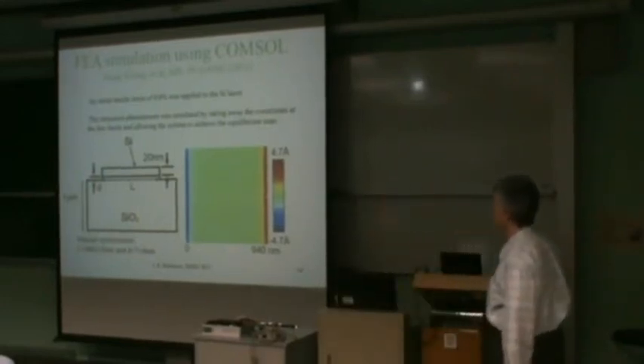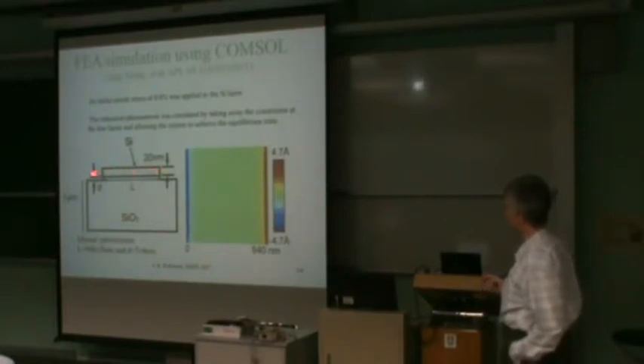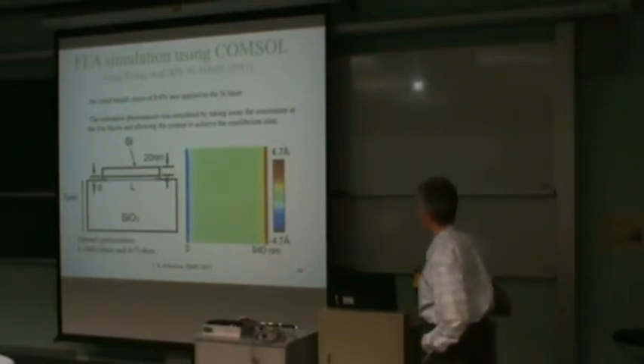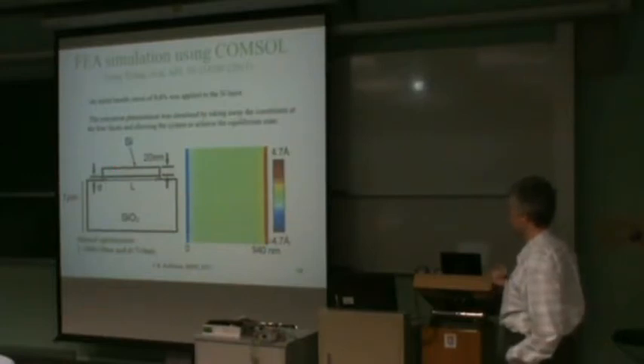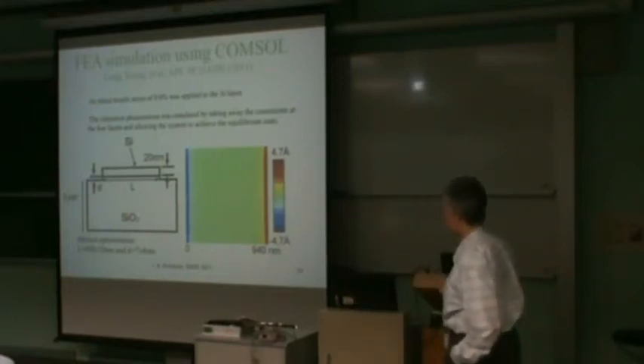This is basically using the method that was described in the previous talk. This was Gang's work, also using the COMSOL package. What he did was construct what we thought we had, which is a piece of silicon on top of a piece of SiO2 with strain present in the silicon, and you can just dial that up in COMSOL. We put in the 0.6%, which was the expected number, and we got a result that looked very similar to what we saw. But we found that the decay length was wrong. The distance was actually shorter in the simulation than in the measurement. The way to fix that disagreement was to allow for the fact that the etching process probably went beyond cutting through the SSOI and actually went a little bit into the oxide as well.